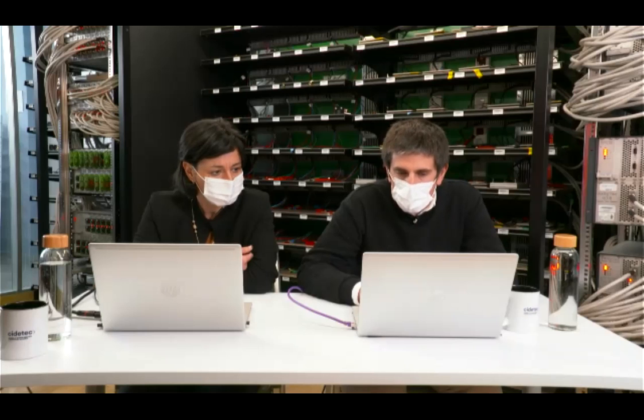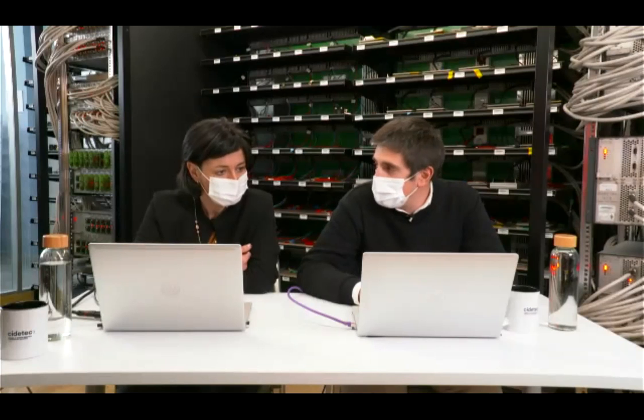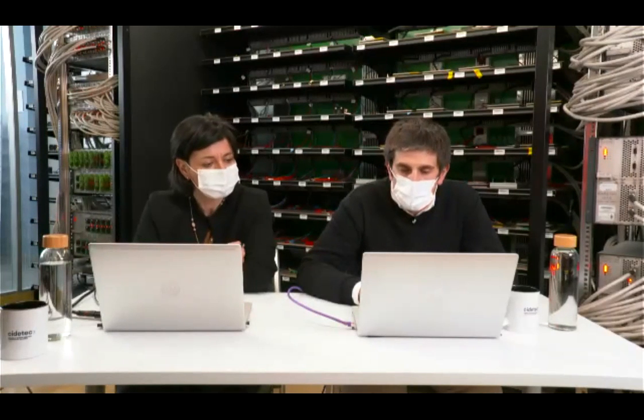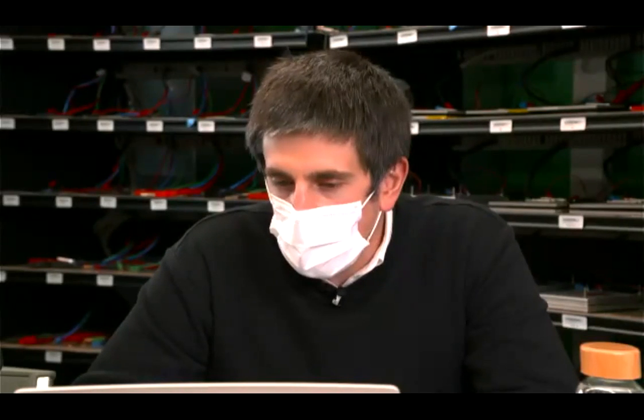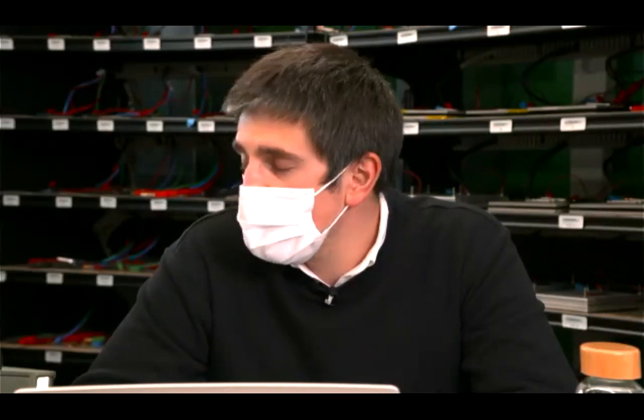So other questions are regarding the current density of this formation cycle. Usually, it's true that there are differences between these formats of the cells, but we have already optimized which densities we are going to use in the formation and also in the test previously in the coin cell. After that, sometimes in pouch cells of a smaller size than these ones, and then we are making this in these big pouch cells.